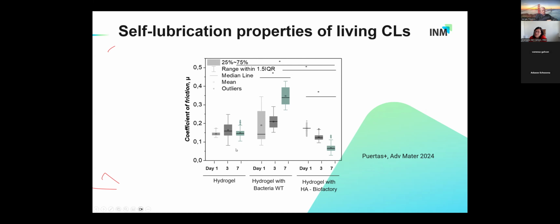Now, when we have the hydrogel, we see no difference over time because we have no factories producing anything. The gel is also stable, so the coefficient of friction remains over time. If this is measured with the supernatant from hydrogels that contain bacteria, then you see that the friction goes up, and this has to do with all the other products which wild type bacteria would secrete. So they deposit on the contact lens. This is also why we have to clean the contact lenses, and we actually see that as the concentration of the secretome of the bacteria goes up, also the friction goes up. And in the case of the lens that contains the bacteria that secrete the hyaluronic acid, the friction goes down, which is what we were, of course, looking for.